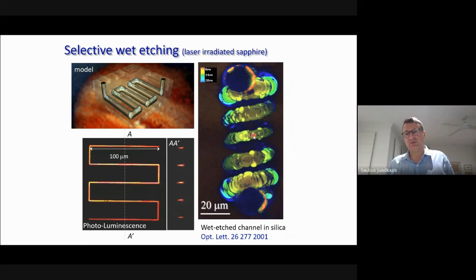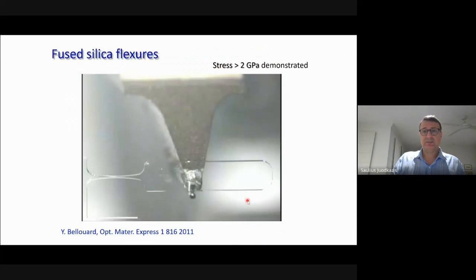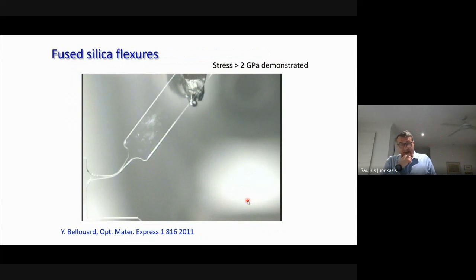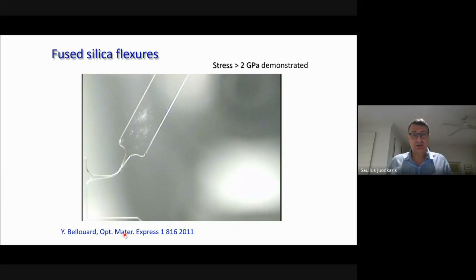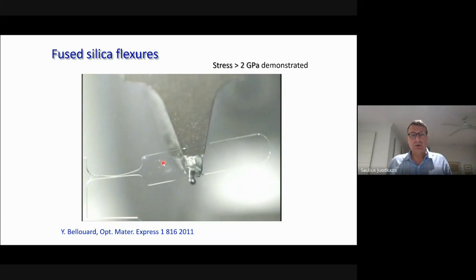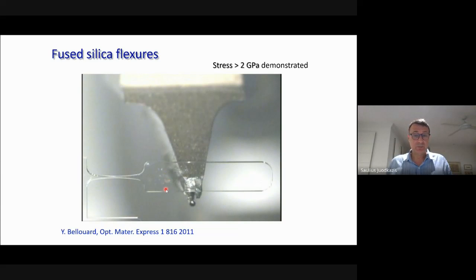The same is true also for glass. Glass only has less contrast, so you see that the channels of the spiral here are larger than the center, because the center was obviously etched later. So we filled it with rhodamine, and this is showing the depths of the luminescence coming out of the 3D structure recorded inside the transparent volume of glass. This is my colleague's work from EPFL, Yves Bellouard. He is making mechanical tools out of glasses, and this is almost unbelievable. This is glass. It's silica glass, which let's repeat one more time.